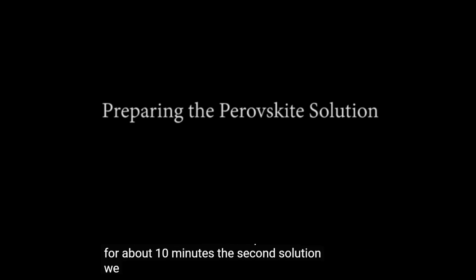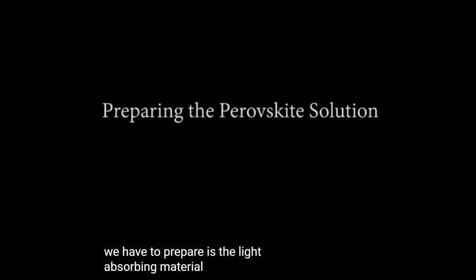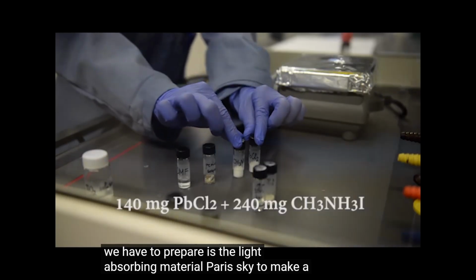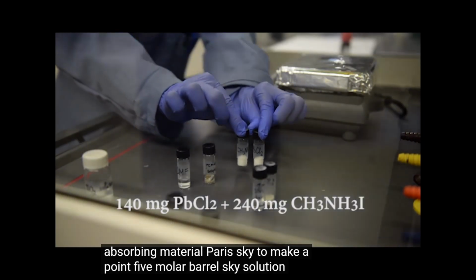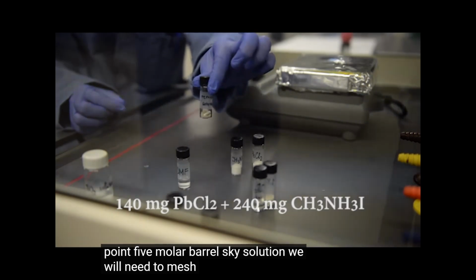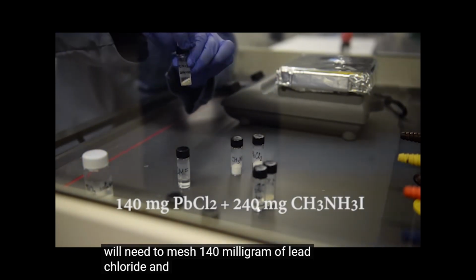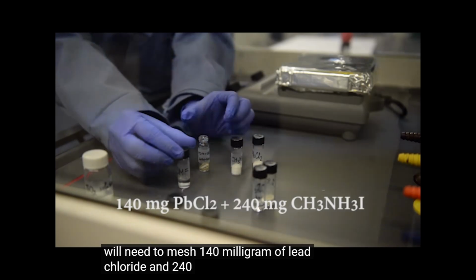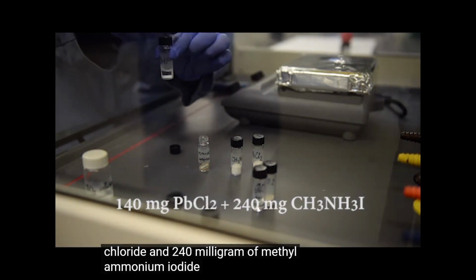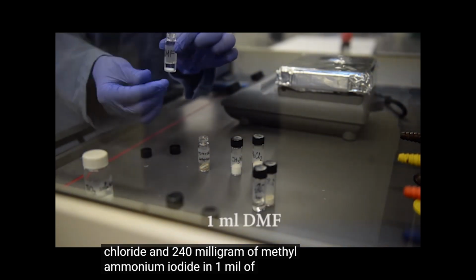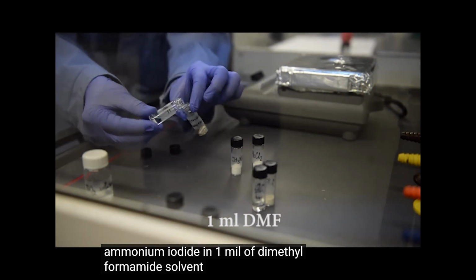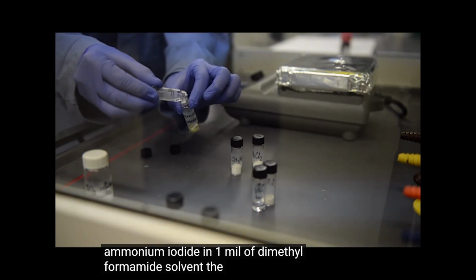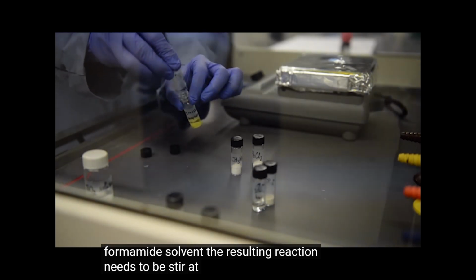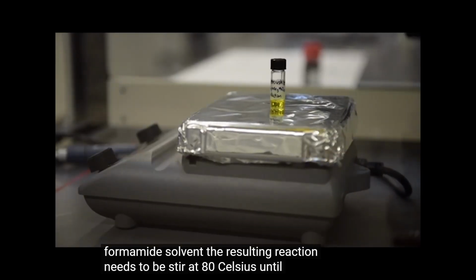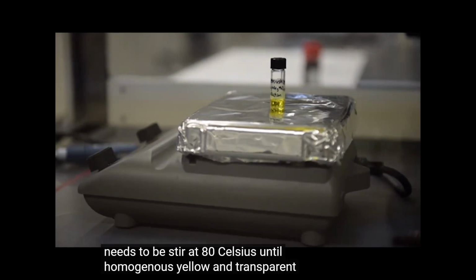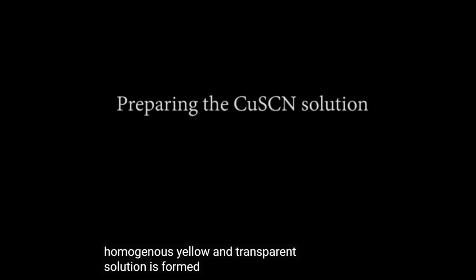The second solution we have to prepare is the light absorbing material perovskite. To make a 0.5 molar perovskite solution, we will need to mix 140 mg of lead chloride and 240 mg of methyl ammonium iodide in 1 ml of dimethylformamide solvent. The resulting reaction needs to be stirred at 80 Celsius until a homogeneous yellow and transparent solution is formed.